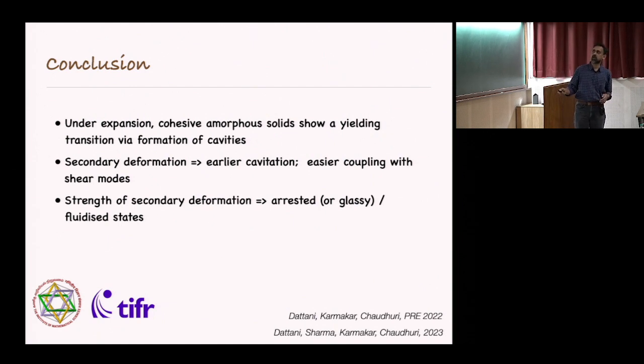To conclude, under expansion, cohesive amorphous solids show yielding transformation by cavitation. We add secondary deformation which leads to earlier cavitation because there's easy coupling with the shear modes. The strength of the secondary deformation would lead to either arrested states or fluidized states. Thank you.